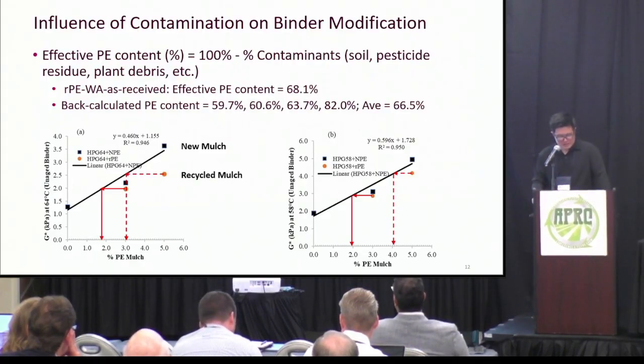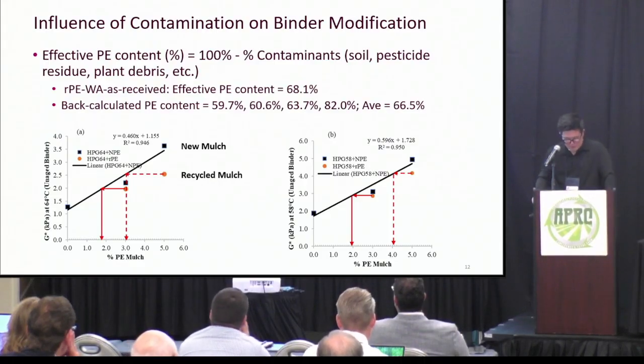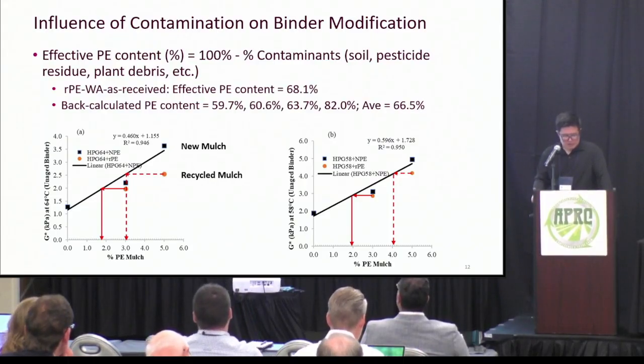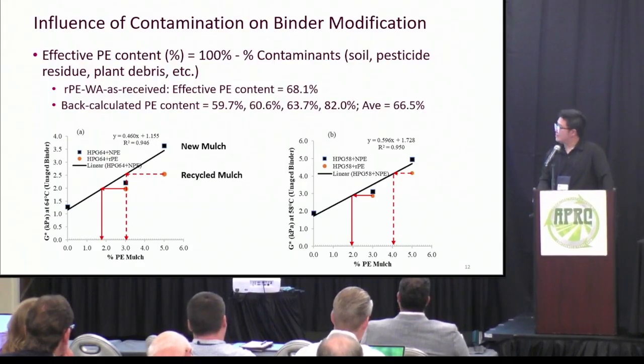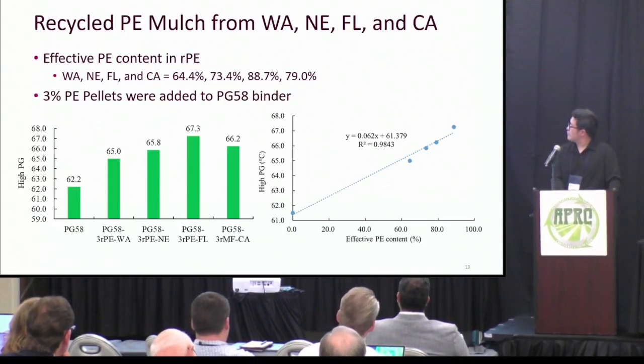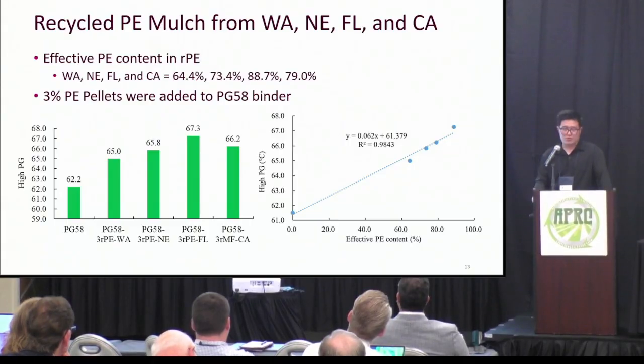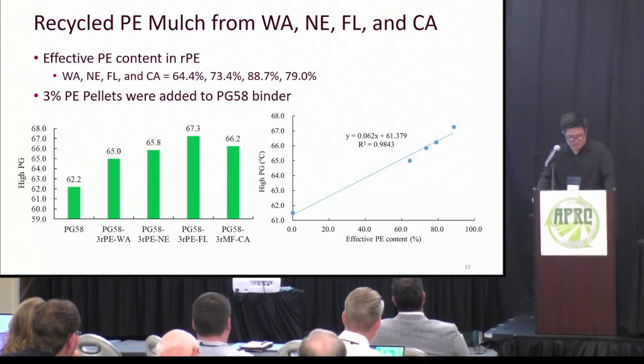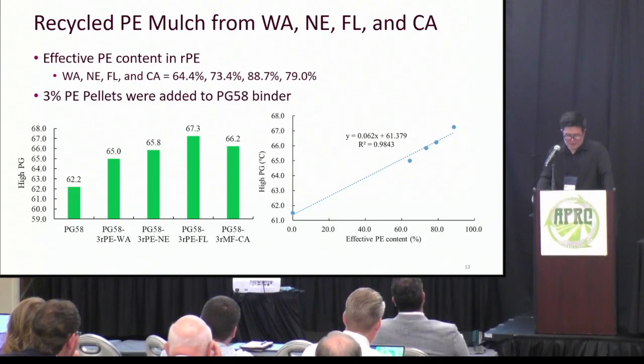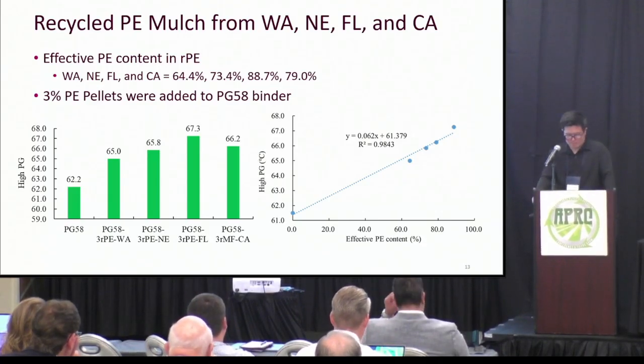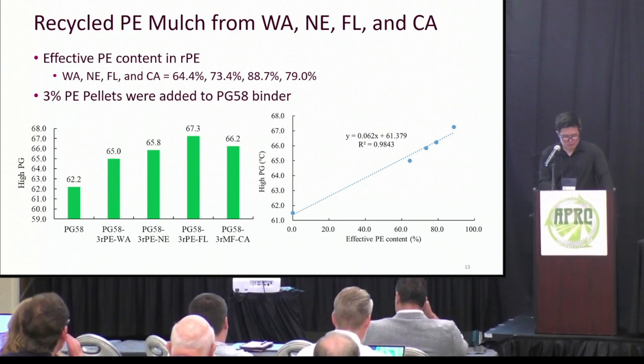So to study the influence of contamination on binder modification, we compared the new PE mulch versus recycled PE mulch. The recycled PE mulch has lower modification than the new PE mulch because the recycled PE mulch has higher contamination. And then to further validate the influence of contamination, we also collected recycled PE mulch from Washington, Nebraska, Florida, and California, and they all have different effective PE contents. We use the recycled PE mulch to modify asphalt. It can be seen there is a very linear relationship between the high PG, or the rutting resistance, and the effective PE content.